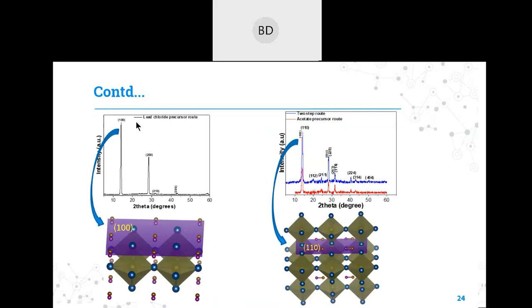If you see the diffraction patterns of lead chloride precursor route, it shows a very good cubic symmetry. Like it has 100 peak, 200 peak, and then 300 peak. So it's a very good cubic symmetry with most of the crystal orientation aligned in 100 direction. But in this, if you see the two-step route and acetate precursor route, the symmetry is a little distorted. Here it is showing 110 alignment, 220, and some other peaks also. So it shows that it's not a perfect cubic structure. It moves toward a tetragonal structure.